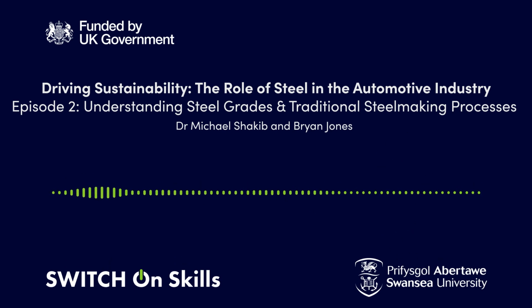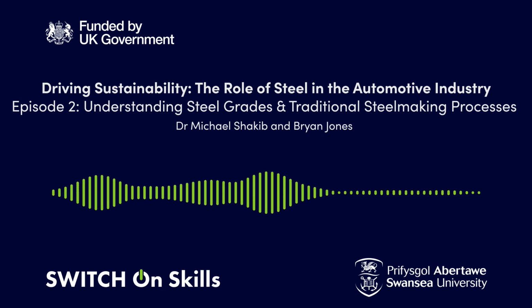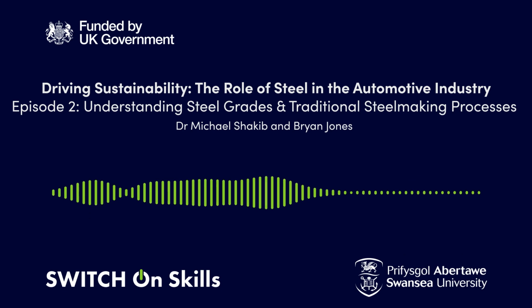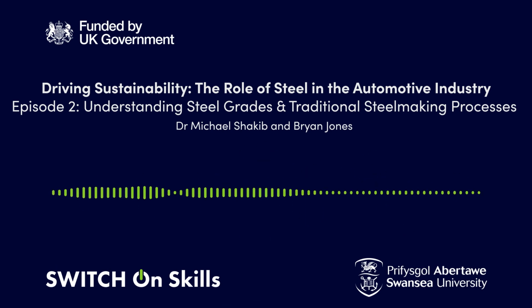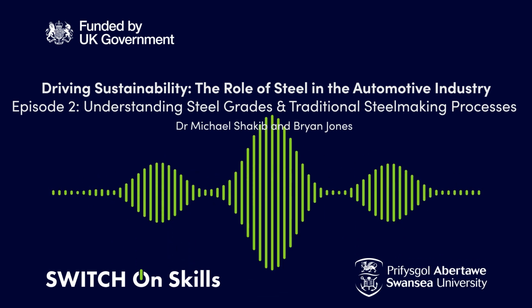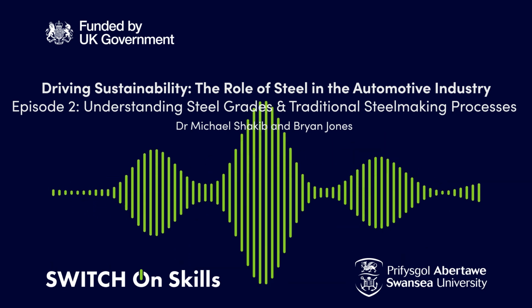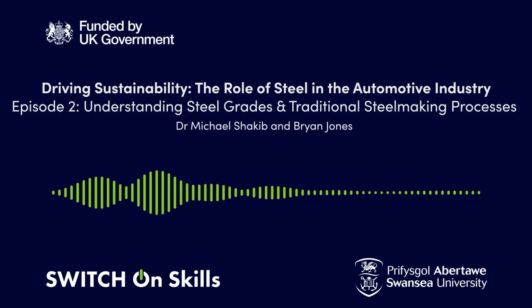Yeah. The other aspect to mention, because the focus is mainly on automotive, is that the product may not be suitable for automotive applications. If you talk about the main grade of scrap steel that's available, typically 75% of the steel is classed as merchant scrap. And in merchant scrap, there's no control in the chemistry, basically. The biggest element of merchant scrap is reinforcing bar, for example. So that contains a lot of tramp elements, such as copper and tin, nitrogen, and other elements which are deleterious if you're making a highly formable grade of steel.